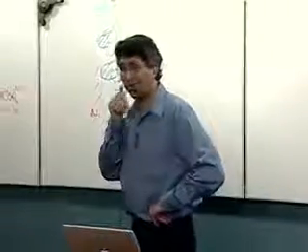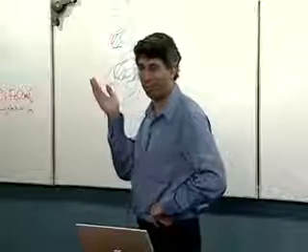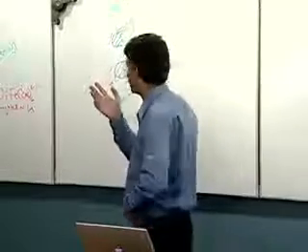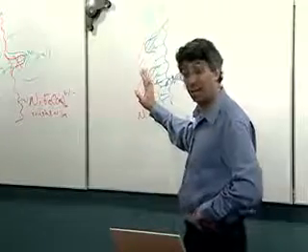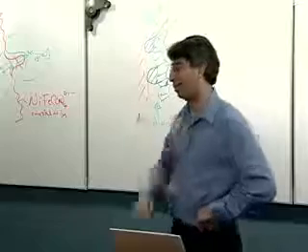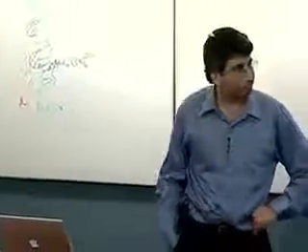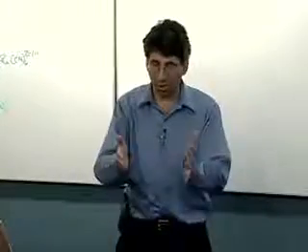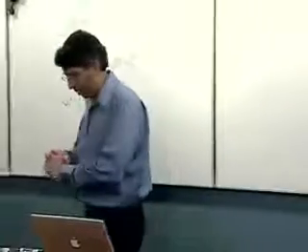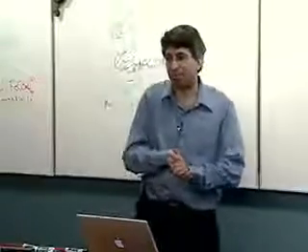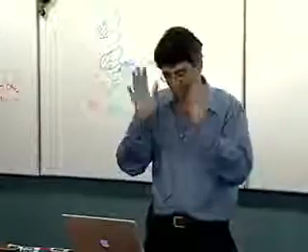It turned out, to make it work for some reason, we knew we had to throw in a few extra nickel ions, which was a little weird. It was totally an accidental discovery. We were trying to figure out how to make these layers really nice, and we threw some extra nickel ions in. And we discovered we only see this catalysis in the presence of an excess of nickel ions. So that was a little confusing. So it works. It needs nickel ions around, and we're very confused by all of this. An excess of nickel in preparing the film? Yes, in preparing it.